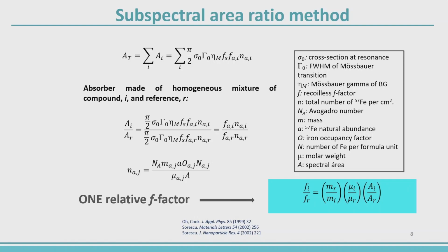We use as a reference material metallic iron powder, which has been well characterized and whose F factor at different temperatures has been reported. For example, at room temperature it is 0.7, so we use this value as a reference, and this formula is very simple. You see that here we have the mass of the reference material, the mass of the sample, the molecular weight of the sample and the reference material, and the Mössbauer spectral areas. So by using this simple formula and determining the relative areas, we can determine the relative F factor. This experiment is very simple. It can be done at any temperature, but we are going to show the results for room temperature, which is usually used in many laboratories.